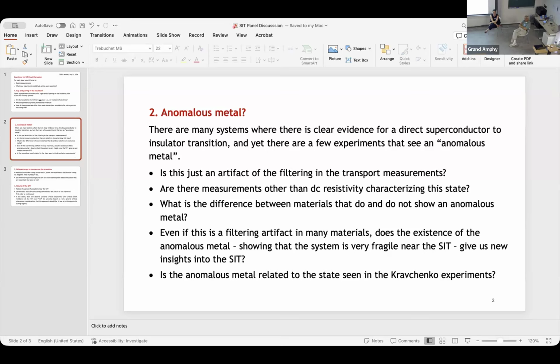Then we found that, of course, for the superconducting state, it's infinite. And for the insulator state, it's almost zero, because it's very localized Cooper pairs. But for the so-called anomalous metal state, the coherence length is short range. It's not localized, but it's not long range. It's several hundred nanometers or so.